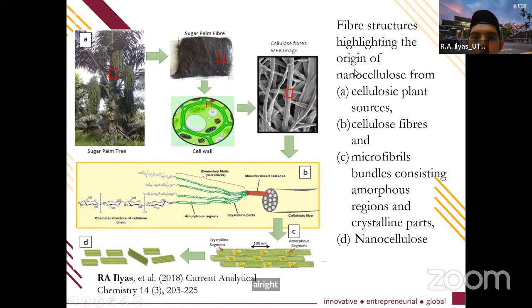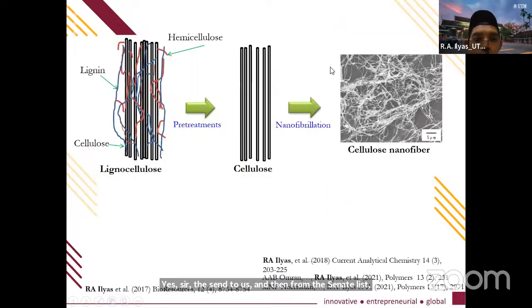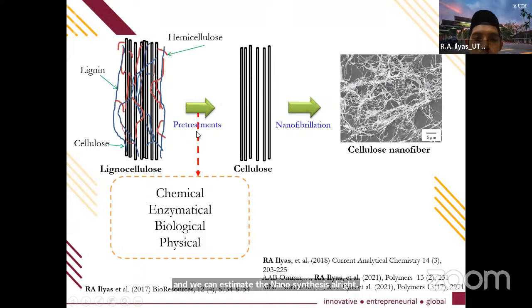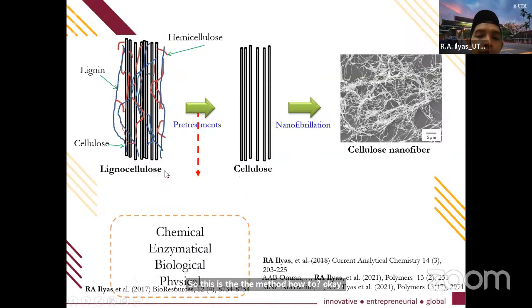This is how we get the nanocellulose from the sugar palm tree. We extract the fiber, and then from the cell wall of the fiber we extract the cellulose, and then from the cellulose we can extract the nanocellulose. This is the method of how to extract nanocellulose from lignocellulosic, or plant fiber.